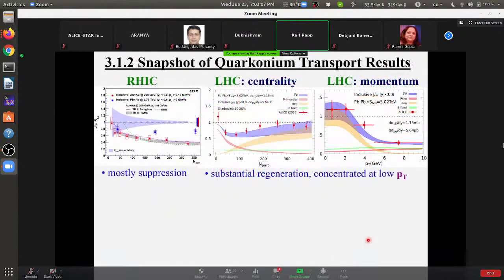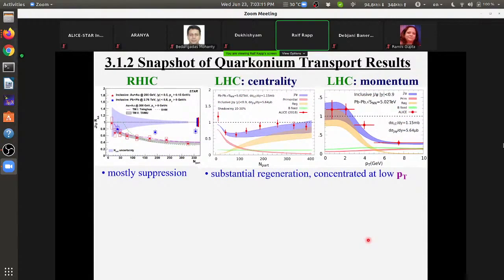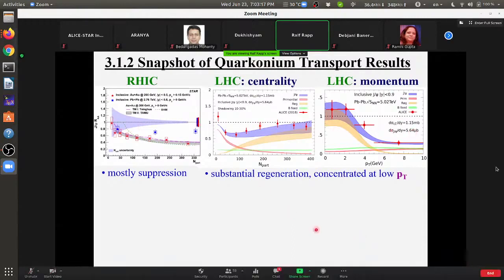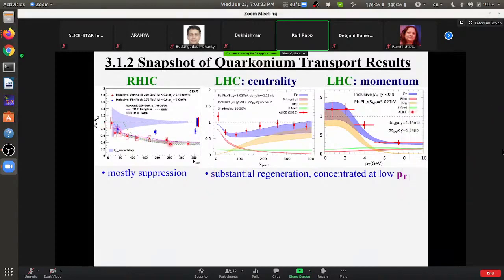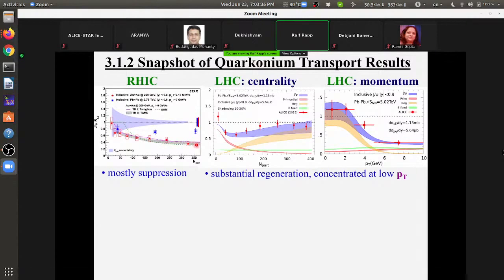I don't want to go into much detail, just give you some snapshot or example of the heavy quarkonium phenomenology that has been developed over the years and how it compares to data. So these are the results for J/psi production. And I should say, of course, you need to also treat the chi-c and the psi prime because they feed down to it. So they are also included in all of these calculations by the various groups. You see the main effect at RHIC is a suppression, although there are already contributions from regeneration, but they are relatively small, maybe half of this, or even a little less. But then you go to LHC and the R_AA really kind of turns around and it's close to 1.